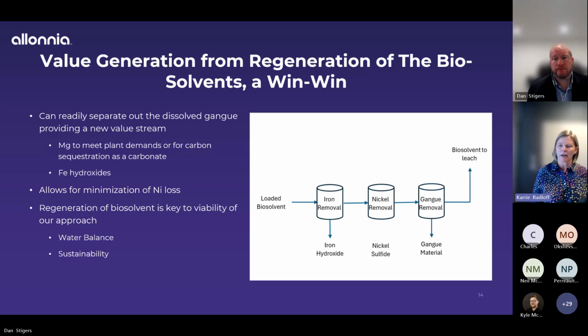This is also allowing us to minimize our nickel loss. If that initial loss of nickel isn't controlled, we can still recover that nickel downstream, so it's not lost out of the process. And we really see that the regeneration of our biosolvent is the key for this being a viable process at a mining site, because we have to be aware of the water balance and the sustainability of our solution in order for it to be adopted and meet ESG goals.